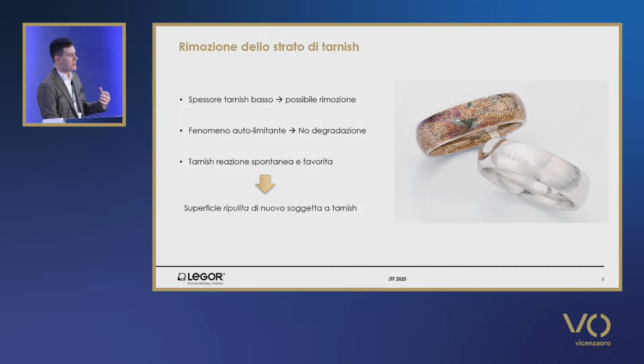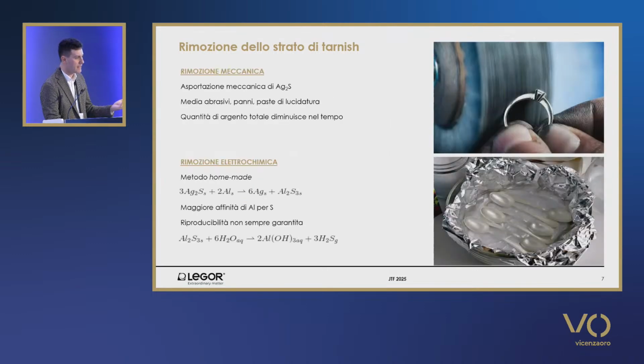And indeed, the tarnish reaction is a self-limiting phenomenon which involves a low layer of the surface, and it is possible as a consequence to remove the tarnish layer, which will not attack the whole bulk of silver as can happen in iron. And as a consequence, once you have removed the layer, the surface of silver will show its proper chemical and physical characteristics. But of course, as the silver layer is exposed to atmosphere, it will be subjected to tarnishing. Well, there are various techniques.